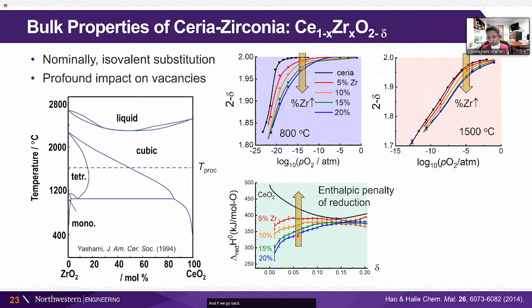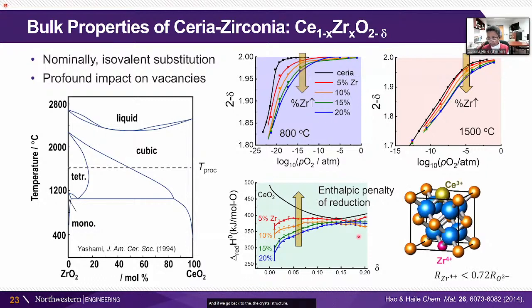And if we go back to the crystal structure itself and the crystal chemistry, what we speculate is happening here is that we have this material which has the fluorite crystal structure. The cations in this system are 8-fold coordinated. Cerium is a large cation, whether it's 3+ or 4+, it's even larger when it's 3+, and it's very comfortable having 8-fold coordination of oxygen ions around it. Zirconium, on the other hand, is not comfortable with 8-fold coordination. In fact, that's why at room temperature it distorts away from the cubic phase to the monoclinic phase. And it wants to have only 7-fold coordination.